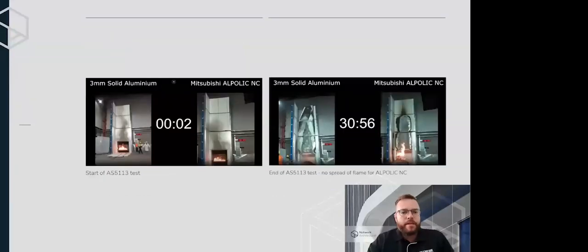So here are two side-by-side slides. So this is 3mm solid aluminum and ALPOLIC NC being tested at CSIRO. So that was the beginning of the test, and on the right is the end of that test at that 30-minute mark. So you can see there that the aluminium has actually fallen off that top of the panel itself, and that has melted significantly. While the ALPOLIC NC on the right, you can see there that it hasn't reached the top yet, and the panels at the top are still fixed on.